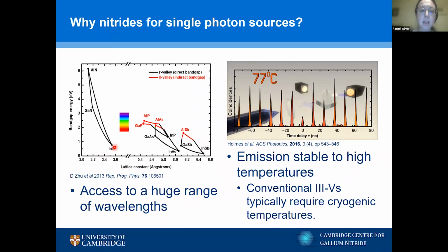Well, one reason is that the nitrides allow us access to a huge range of wavelengths, from indium nitride in the infrared out to aluminium nitride in the ultraviolet. And where we might require different wavelengths of emission for different applications, the nitrides have the potential to enable that all across a single materials family. The other thing that's really exciting about the nitrides is that quantum dot single photon sources in this system continue to operate up to high temperatures. Mostly devices based on this kind of arsenide phosphide type material system only work at a few Kelvin to a few tens of Kelvin.